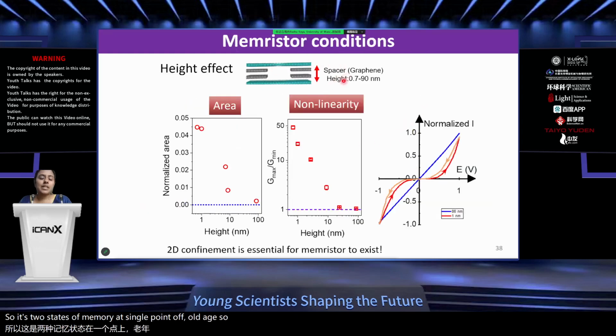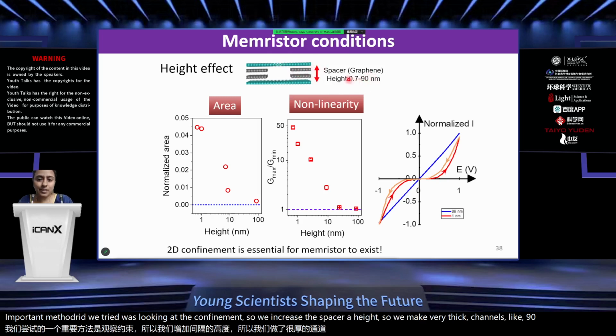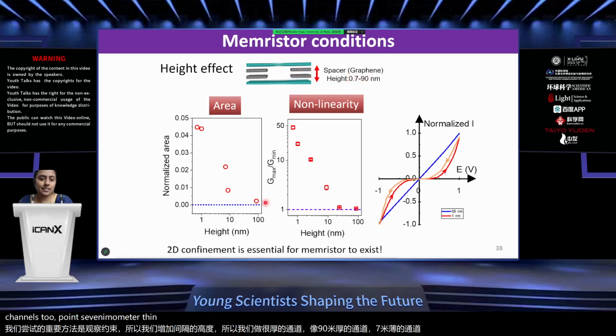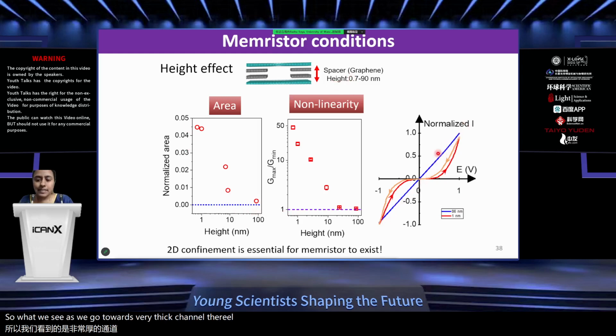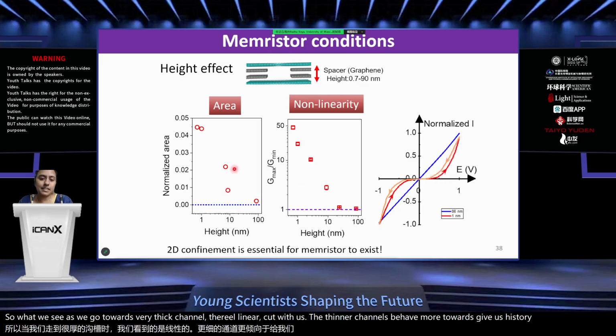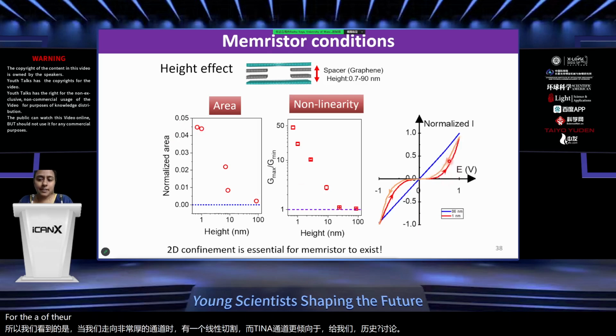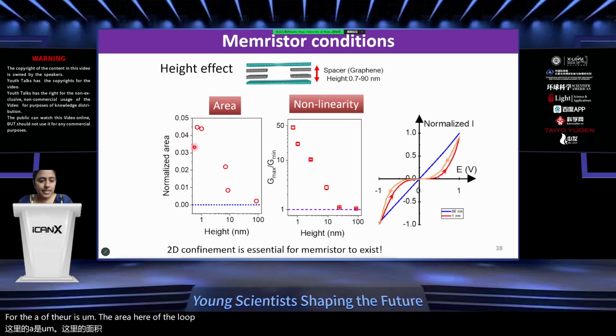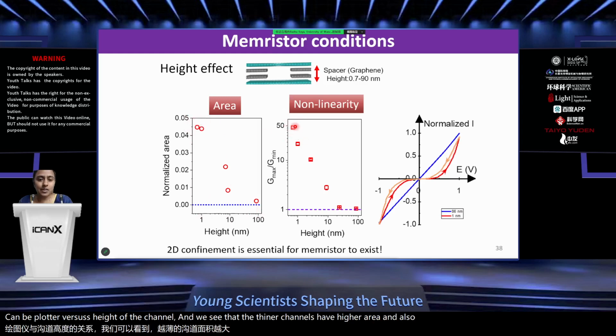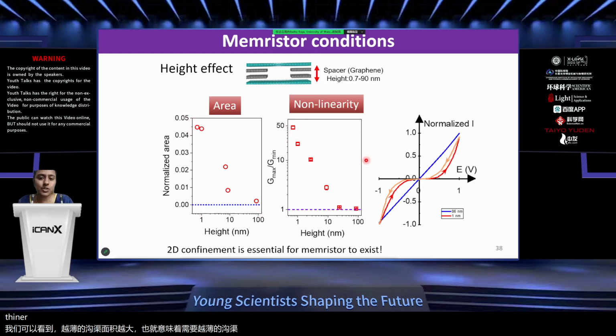So how does this memory come about? The first important metric we tried was looking at the confinement. So we increase the spacer height. We make very thick channels, like 90 nanometer thick channels, to 0.7 nanometer thin channels. What we see is, as we go towards very thick channels, there is a linear curve, whereas the thinner channels give us hysteretic curves. The area of the loop can be plotted versus height of the channel, and we see that the thinner channels have higher area and also higher nonlinearity. That means you need thinner channels to get the memory.